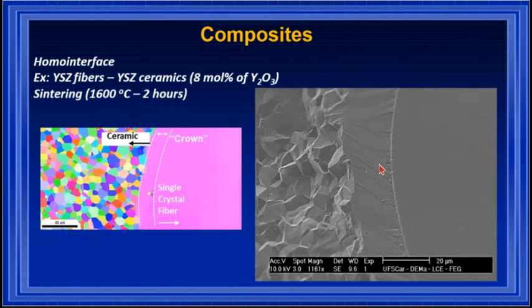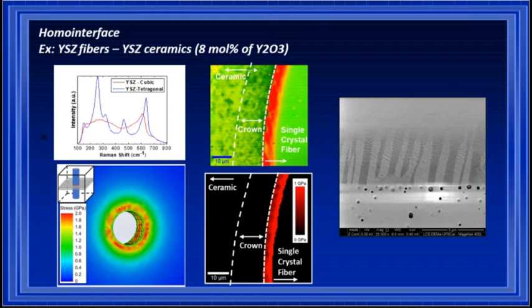This interface, in the case of the ceramic, we call it crown, because it surrounded all the fiber. The Raman measurements in these composites have shown us that in this region of the interface, we observe a phase transition at the surface of the fiber from cubic to tetragonal zirconia. We believe that this occurs due to the high pressure that is involved in the sintering process.